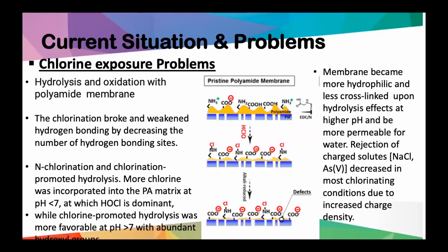Okay. On the other hand, we can see another important problem, which is chlorine exposure. In our desalination plants using RO membranes, we are pre-treating the water. One of the main steps of the pre-treatment is disinfection. One of the important disinfecting agents used is chlorine. One can ask why we use chlorine to disinfect before the RO modules. We need some pre-treatment stages before using RO, and if we do not disinfect, or kill the microorganisms and the sources of algal or bacterial growth, they increase more and more and will clog the pre-treatment stages.